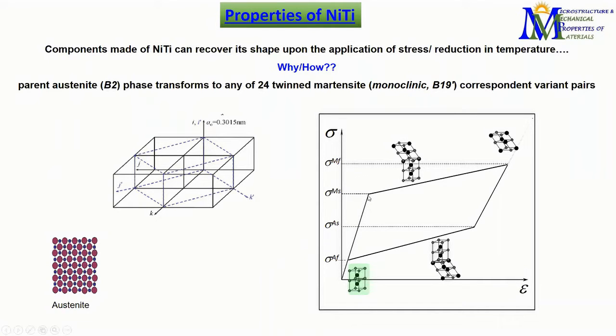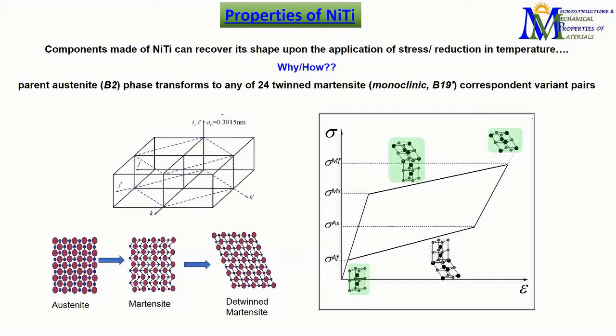If we apply stress, at a certain value of stress, it starts to convert to martensite. This martensite has a monoclinic structure, B19 prime. So it converts to this. After that, there is an amount of strain within which this conversion of austenite to martensite is going on. Then there is another formation, which is the detwinning of the martensite. The martensite which is initially formed is in a twin structure. If we keep on applying stress, the stress application is actually very minimal, but we can see a large increment in the strain value. This is because of the stretching of the martensite, or the detwinning. This is also called reorientation.